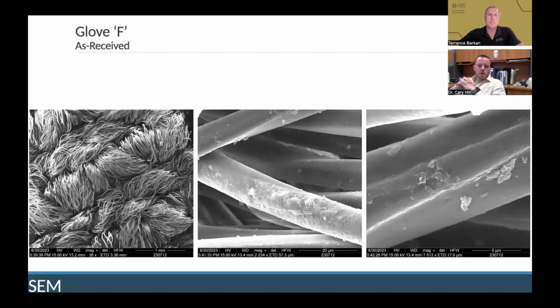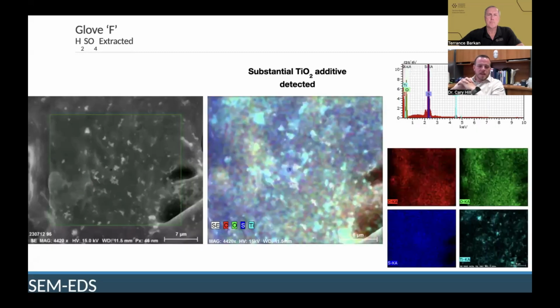Glove F, this is one of the newer ones we've added since that original study. This is just a view of the fibers. Nothing particularly to see here except for some additives on the surface that could be actual particles from ambient sources or from the production itself. And in the next slide, we got the extraction. This one was interesting because we found titanium dioxide was present. Titanium and oxygen signatures overlap in that EDS spectra. So we're seeing titanium dioxide particles that were placed in there as the cut resistant additive. Again, no evidence of graphene in any of the work that we had done.